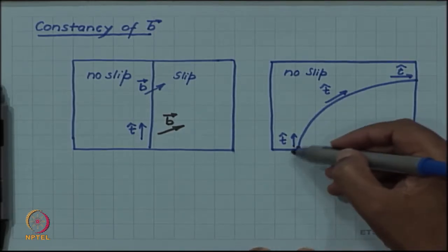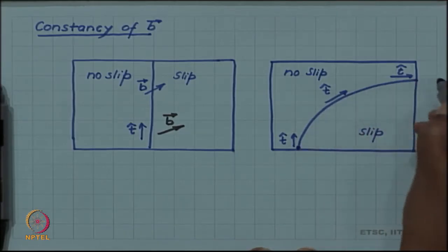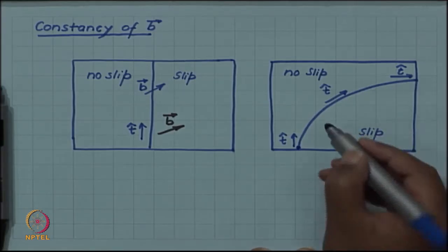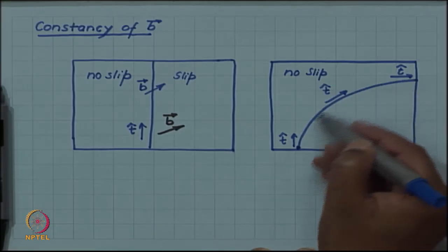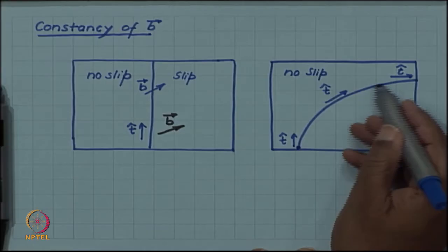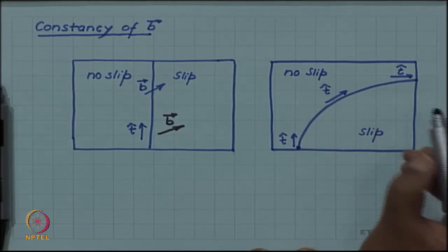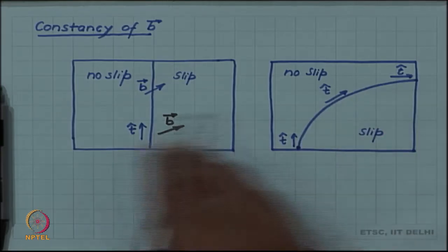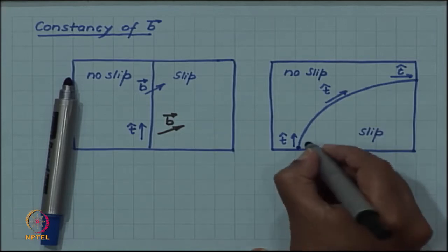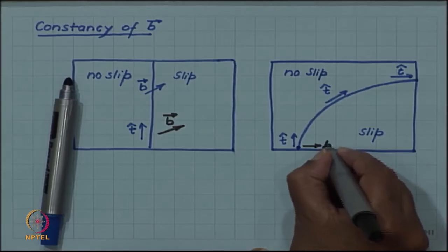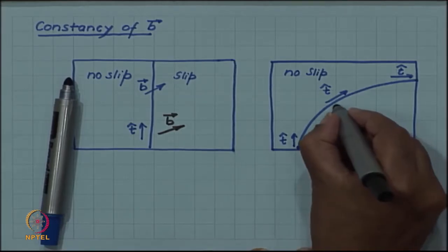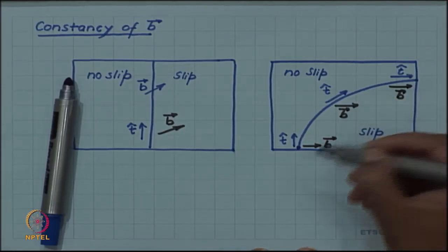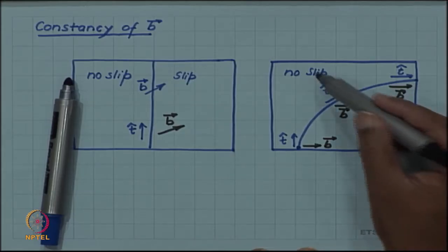To be consistent, the T vector along the line as it changes should have the same sense — it should appear to follow a current flowing along the line as a wire. I should not flip T as I go along the line; it should appear as if a current is flowing along it. So a consistent set of T vectors along a curved line means the tangent is changing, but since we still have a single slip, the Burgers vector will remain the same — for example, a horizontal Burgers vector will remain horizontal at all locations of the dislocation line.